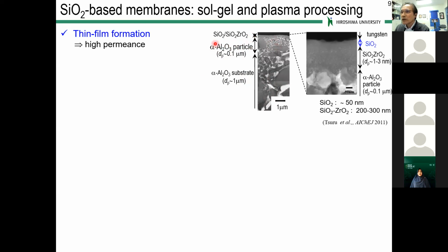On this alpha alumina particle layer, we further coated silica-zirconia intermediate layers, which have a pore size of 1 to 3 nanometers, with a thickness of around 200 to 300 nanometers. On this intermediate layer, we further coat a silica top layer with a thickness around 50 nanometers in this TEM picture.